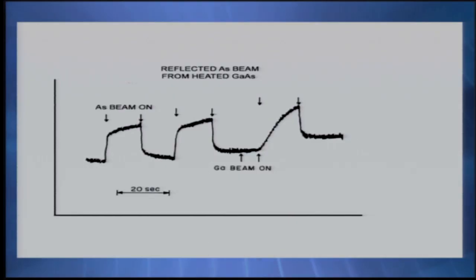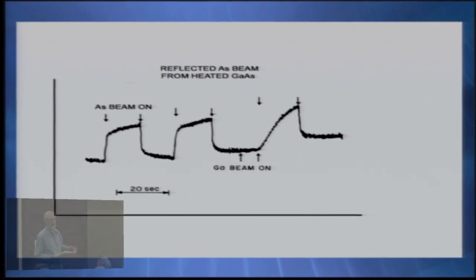The next slide, please. So I tried it with arsenic. Tried doing the same thing with arsenic. And in arsenic, the behavior was quite different. Now, you can see that when I turn the beam on, there's an abrupt rise. There's no decay in the rise. And there's a gradual increase in the arsenic beam coming off just because the background arsenic pressure is getting higher. But then when I turn the beam off, it comes right back down. So we've got basically square pulses.